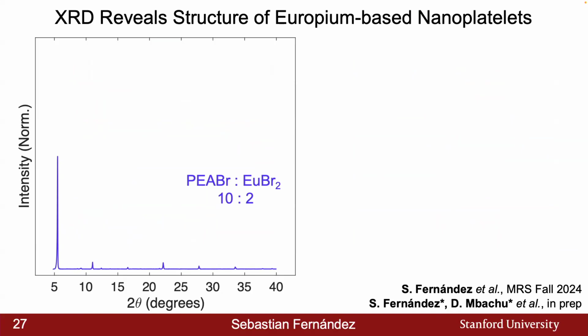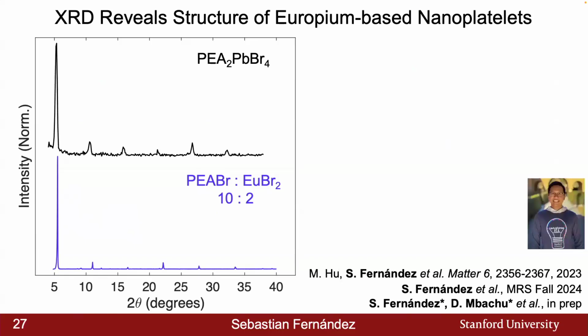Now, we can't directly compare with the previous authors because not only do they have a change in the metal, from europium to lead, but they also have a change in the organic spacer cation. And we want to make as close a comparison as possible. So the most likely candidate in our hypothesis is that the structure is very similar to something like phenethylammonium lead bromide, just an alternative metal case. And luckily we didn't have to go too far, because my colleague Manchen was able to characterize the XRD of these 2D perovskite nanoplatelets.